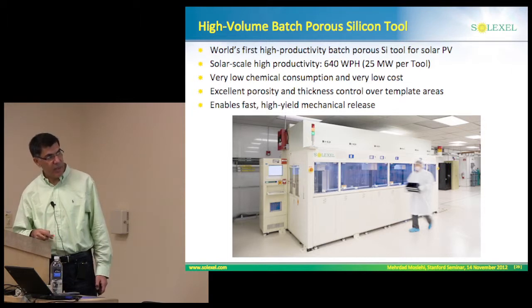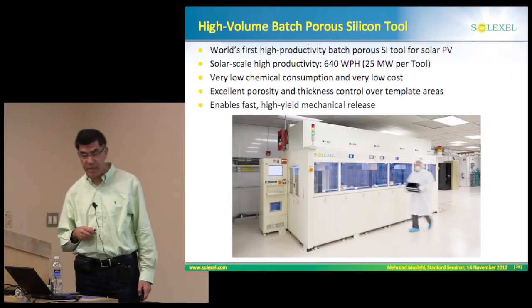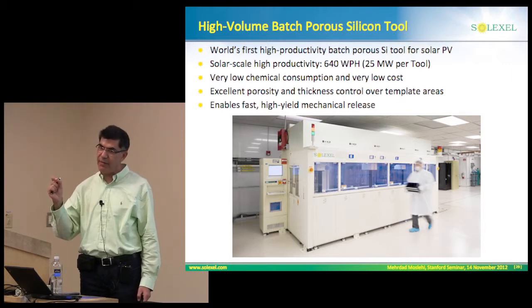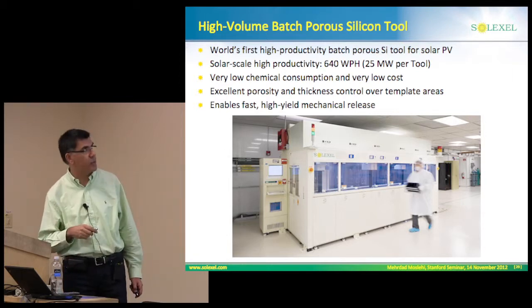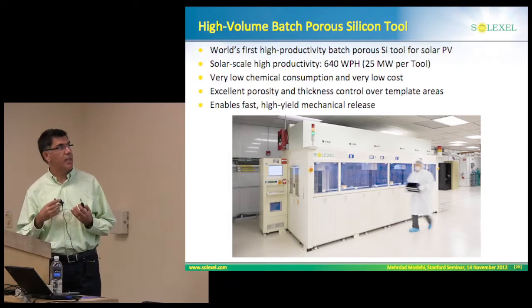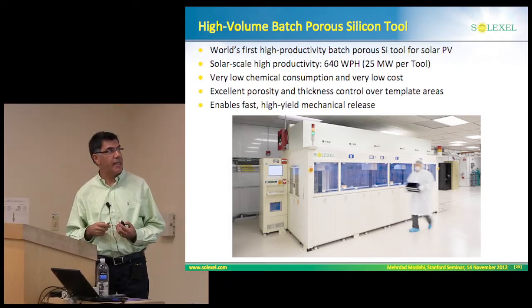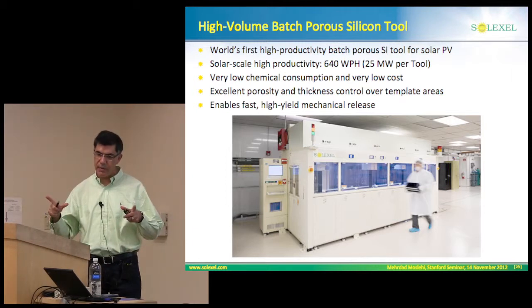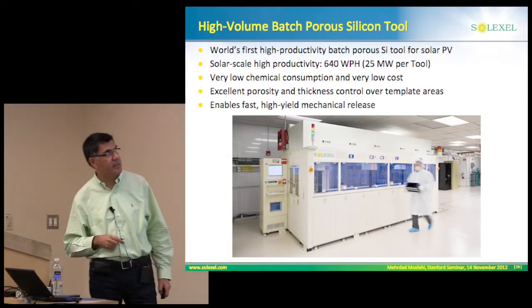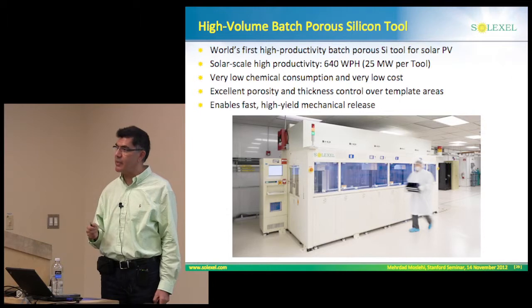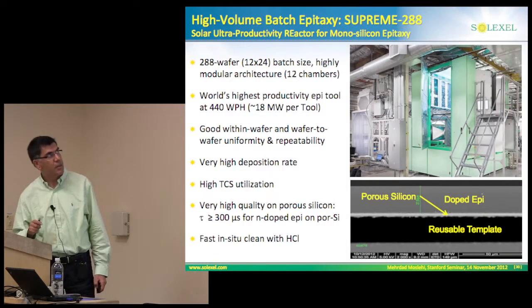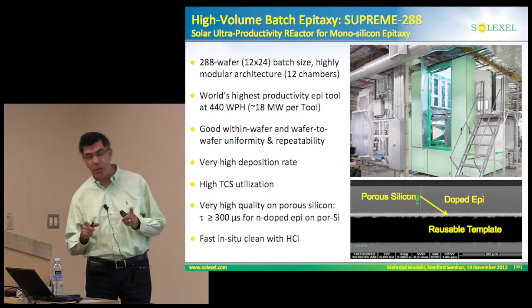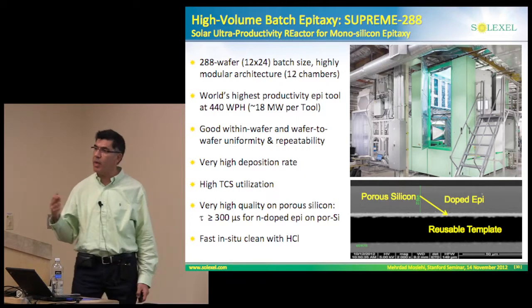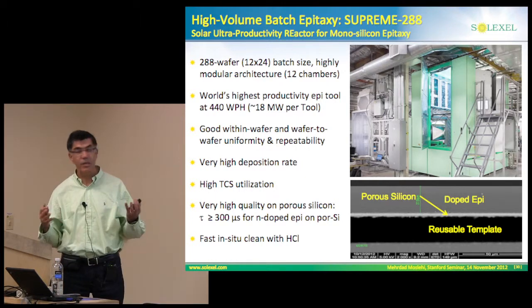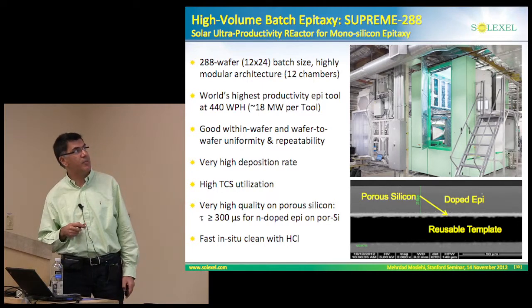And we form porous silicon with very low chemical consumption and very low cost. Our cost is about 1.5 cents per watt with this porous silicon tool. And excellent porosity and thickness control over the entire template areas. And it's also important that this tool, because of the consistency and uniformity that it provides, enables us to achieve very fast mechanical release with extremely high yield. The other tool, which we call Supreme 288, is our high-volume epitaxial tool. It has a highly modular architecture. This is, again, I believe, the world's highest productivity epi tool. It's an atmospheric pressure epi tool, modular architecture, 288 wafer batch size.